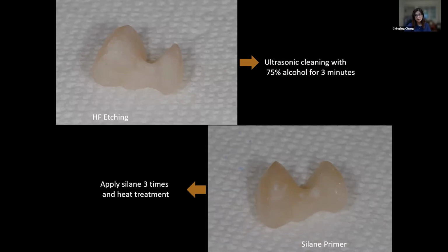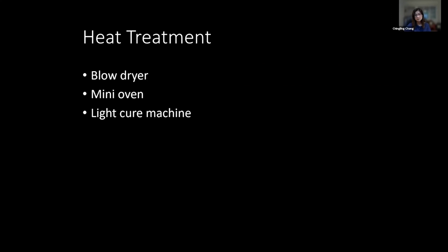And after you apply the silane, the heat treatment is required. Basically, we apply the heat on the silane, so we remove the multiple layers of silane molecules to increase the chemical bond strength. You can use a blow dryer or oven. This has been mentioned by Dr. Pascal Magne. And I like to use a blow dryer because it generates heat too, and it's also very easy to get.